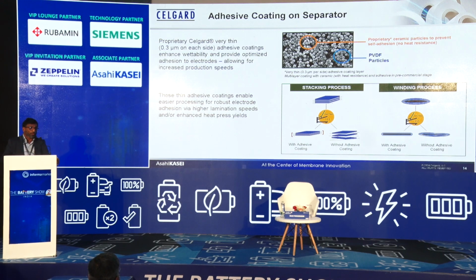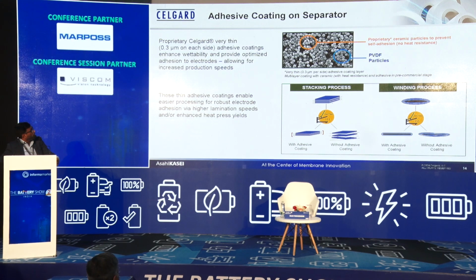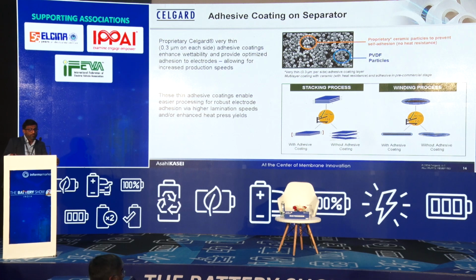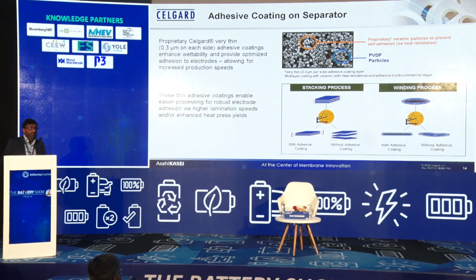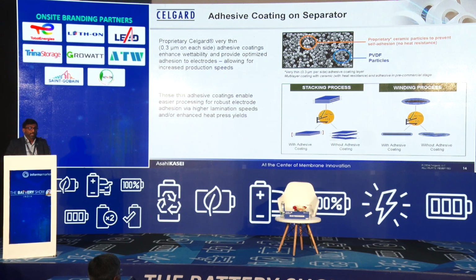And the next coating that we would like to introduce is adhesive coatings. You might have heard that most of the companies are now moving across to prismatic or pouch cells. When you have prismatic or pouch cells in high volume manufacturing, there may be chances that the plates will get shifted away from the separators and get exposed, which causes shorting of these cells. So adhesive separators can hold the plates in the right position, so that the plates will not get exposed and your yield can go up.